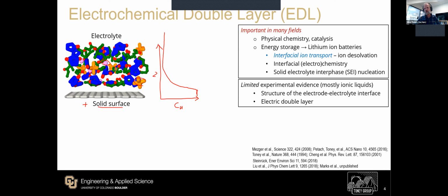The double layer has been known for a long time, but there still is limited information on this. We don't really have a good sense of what's going on, even from a static case. And then that gets back down to, okay, from a dynamic perspective, what are the timescales associated with these various processes, with the formation of the double layer, the exchange between electrolyte molecules here and electrolyte molecules that are in the bulk of the solvent? There's not a lot of experimental data on that. So that begs the question of whether we can potentially use something like XPCS to go after this.